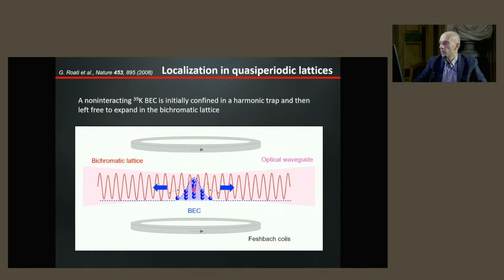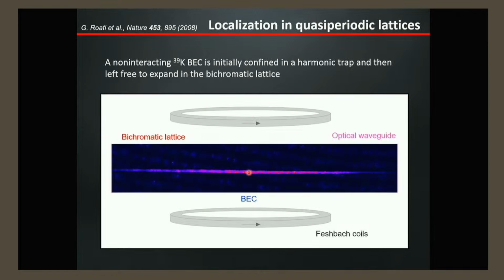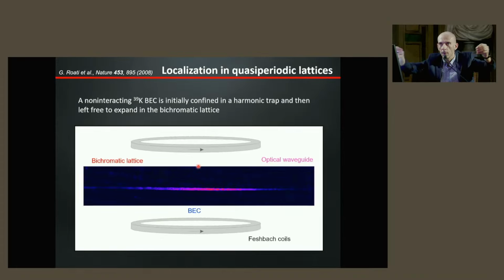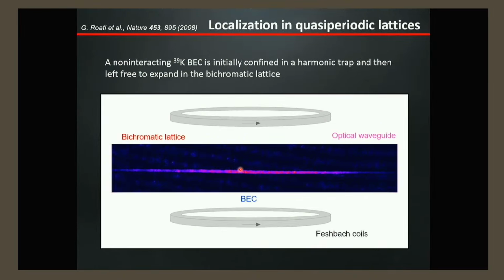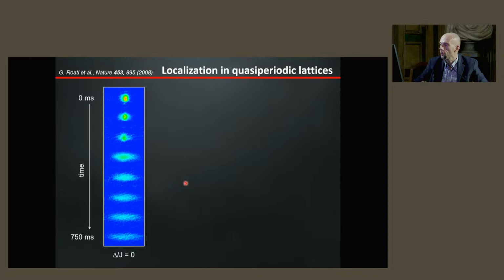So we can perform time-resolved measurements in which we study and measure how these atoms will expand in this one-dimensional quasi-periodic lattice. Here we don't see the lattice itself because it's so thin that this imaging system wasn't good enough to resolve the single sites of the lattice. So this is some kind of coarse-grained density distribution, and here I plot the same kind of pictures as a function of time.